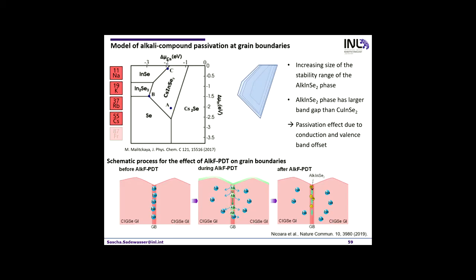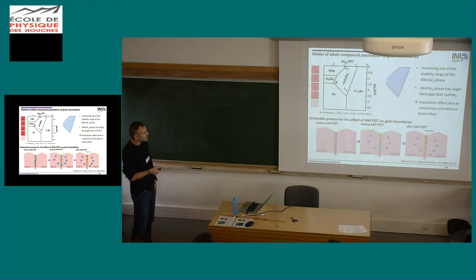And at the same time, they also said that the band gaps of this phase are quite large. So that can explain a passivation effect due to a conduction and valence band offset. So that's a bit the model that was already there partially before, which we extended a little bit.